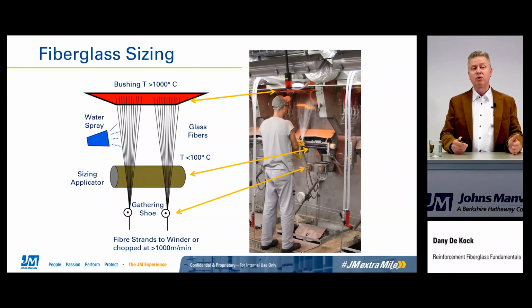So we need to cool the material because bushings are very hot. They are over 1,000 degrees, 1,100 degrees. And how do we cool that fiber? Because we pull at very high speeds. And with very high speeds, I mean super high speeds. It's not really that you can follow what is happening. In 0.3 seconds from the bushing until the winder, we need to cool down from 1,000 degrees to around 50 degrees or lower. And in the meantime, we need to apply the sizing so that the product is usable for customer needs.